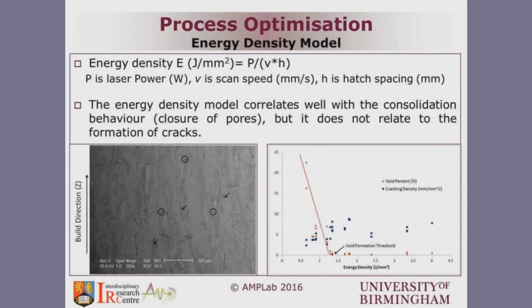In many cases, the challenge is we have two problems to solve. As you can see in the left-hand picture, there are cracks, the ones arrowed, and porosities, which are encircled. We're trying to see if we can reduce both at the same time. In many cases, reducing porosity means giving high energy, but reducing cracking means giving lower energy, because the higher the energy, the more residual stresses we create in the material.